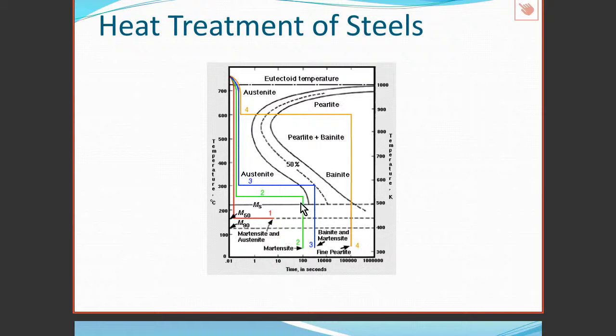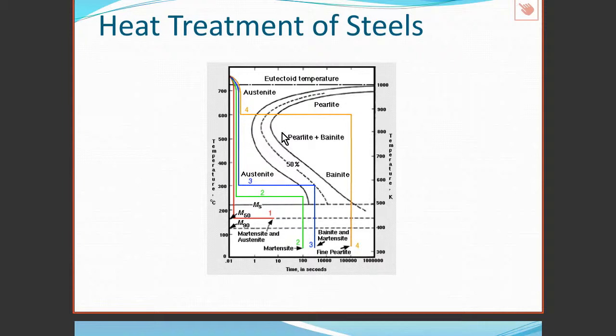You may wonder why these transformation curves have a nose. At high temperatures, although diffusion is very fast, the reaction is not very energetically favorable, so it proceeds sluggishly — the rate is slow. At lower temperatures the reaction is more favorable but diffusion is lower, giving a low reaction rate. Somewhere in the middle we hit a happy median where we have the maximum transformation rate — meaning the material transforms into its final state after the shortest time interval. That's why these curves form a nose.